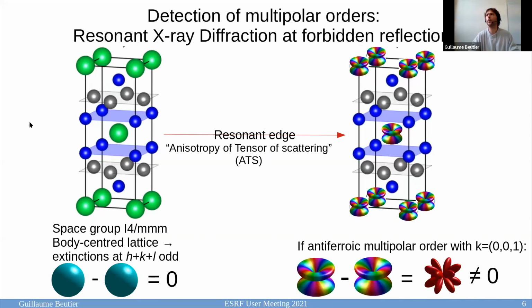So how can we detect multipolar orders with resonant X-ray diffraction? So your best hope is that you're going to observe that you have an antiferroic order, because in that case you could observe this antiferroic order at forbidden reflections of the unit cell. So here, because it's a body-centered lattice initially, and if we have antiferroic order with propagation vector 001, we could have pure antiferroic reflections appearing at the forbidden reflections.